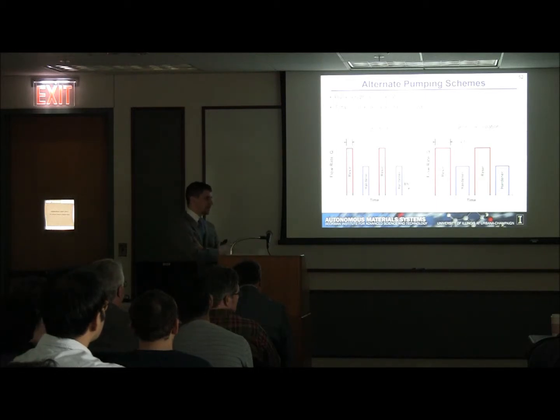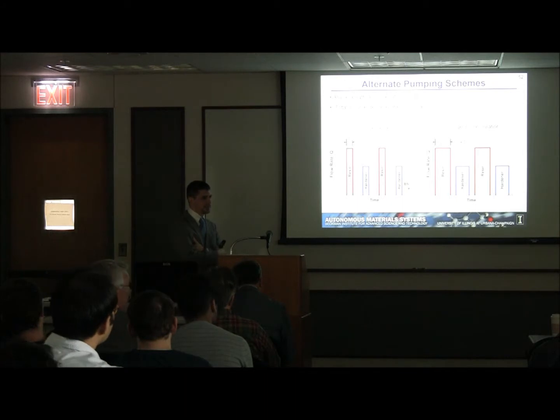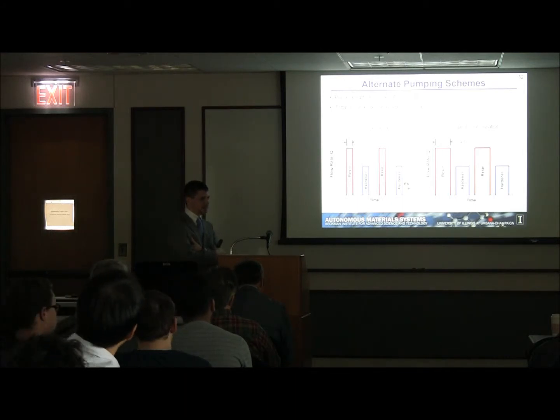So the impact is on the order of 30 to 50 microns for my specimens. Yeah. And the DCB, so I do have a binder clip on where the hinges are as it's being healed. And I did put that under the microscope and look at it, and it ranges from about 12 to 30 microns.